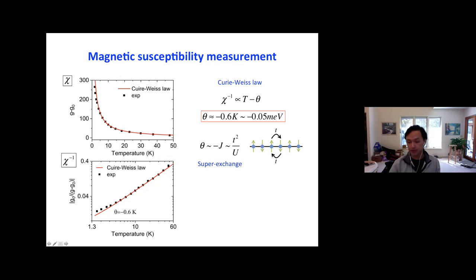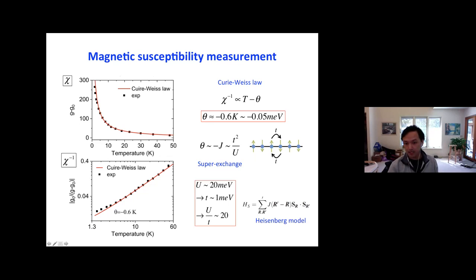We have estimated U from the temperature measurement, which is a lower estimate. It's about 20 meV. And since we have measured theta, we can estimate t. t is about 1 meV, which agrees very well with an initial band structure calculation that gives a bandwidth of about 10 meV, but the bandwidth is about 6, so t is about 1.5 meV from calculation. So this is not that bad. And when you do U over t, it's about 20. So the system is really in the strongly interacting regime.